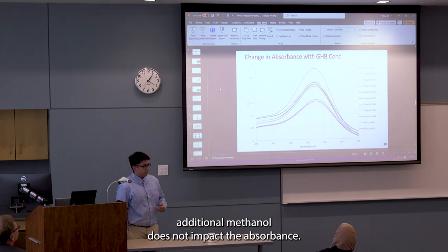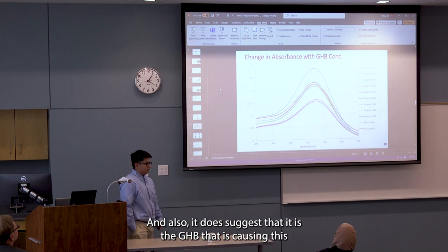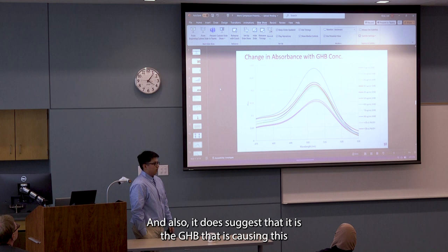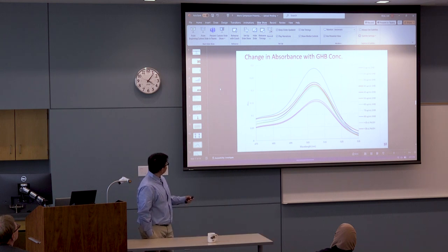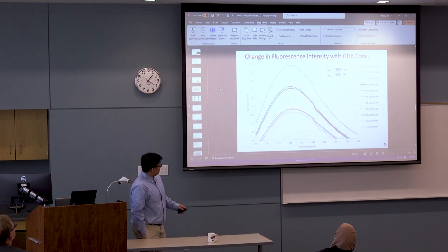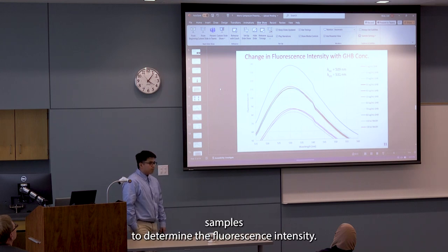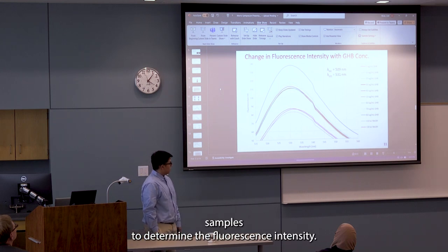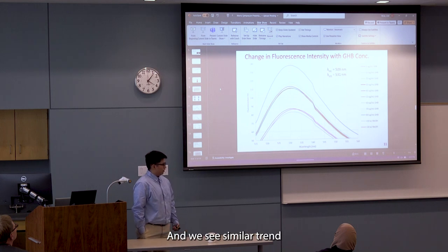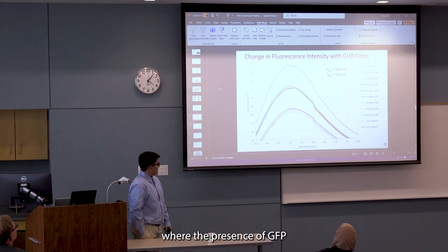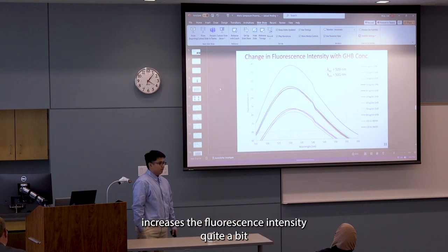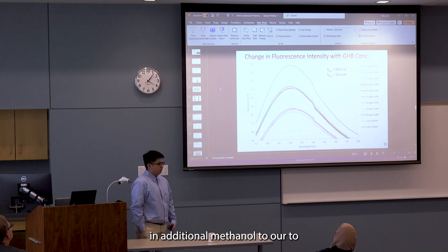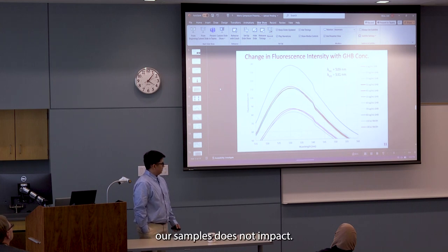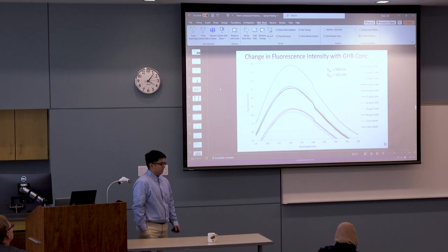We saw that adding additional methanol does not impact the absorbance at all, so it just suggests that it is the GHB that is causing this increase in absorbance. We analyzed the same samples to determine the fluorescence intensity, and we see a similar trend where the presence of GHB increases the fluorescence intensity quite a bit, and additional methanol to our samples does not impact the fluorescence intensity.